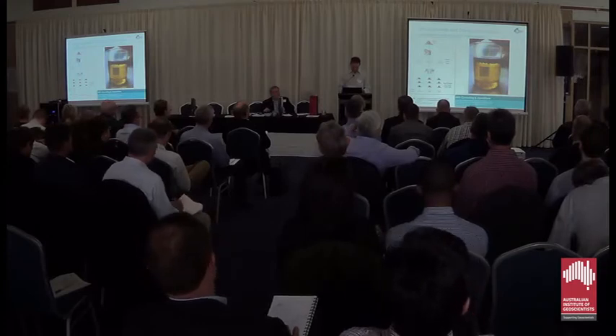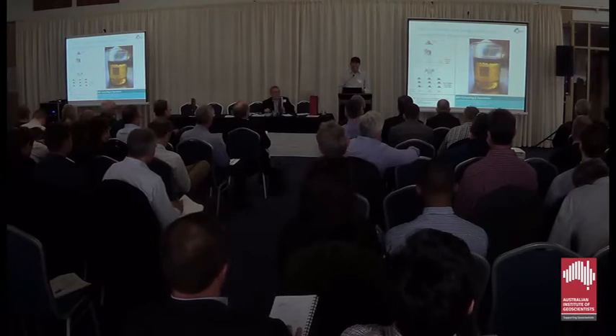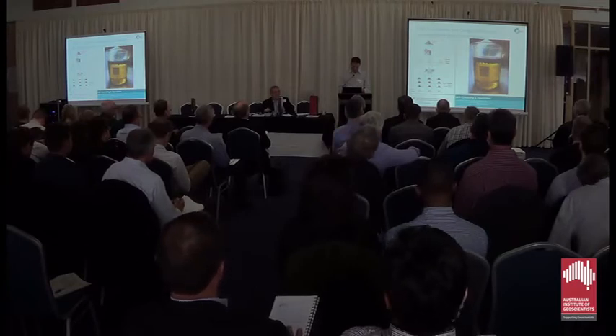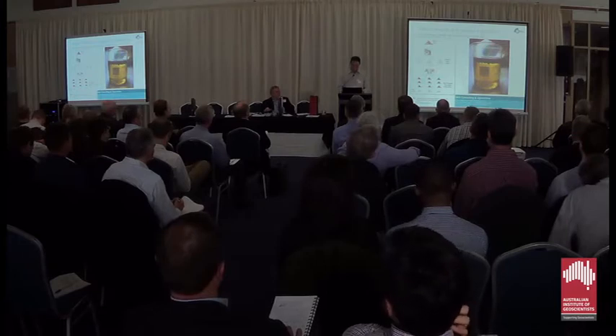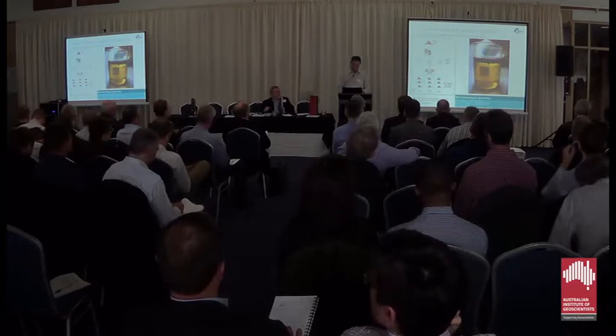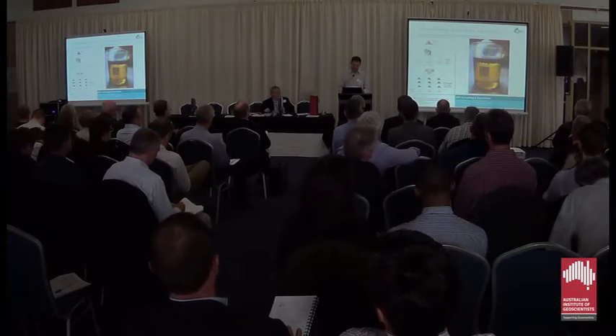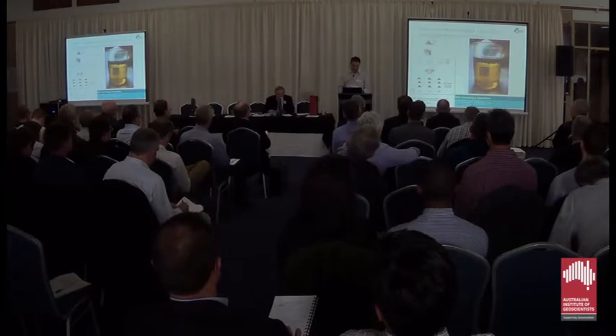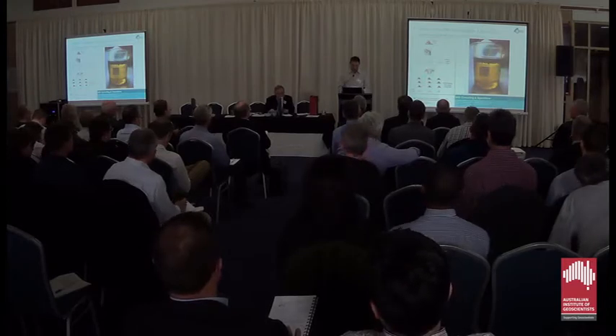The coarser the grind size, the less losses to the fines fraction. However, the amount of spodumene reporting to the middlings fraction and subsequently the fine circuit will increase. The finer the grind size, the higher the losses to the fines fraction. However, the amount of spodumene lost to the middlings fraction and subsequently the fine circuit decreases. In the end, the recovery of coarse spodumene at a saleable grade will win out.